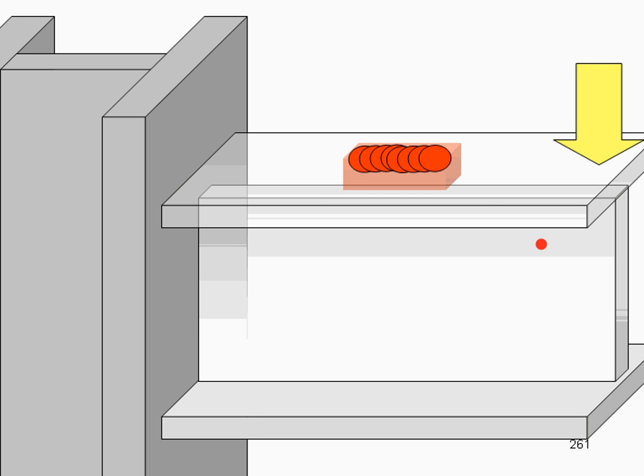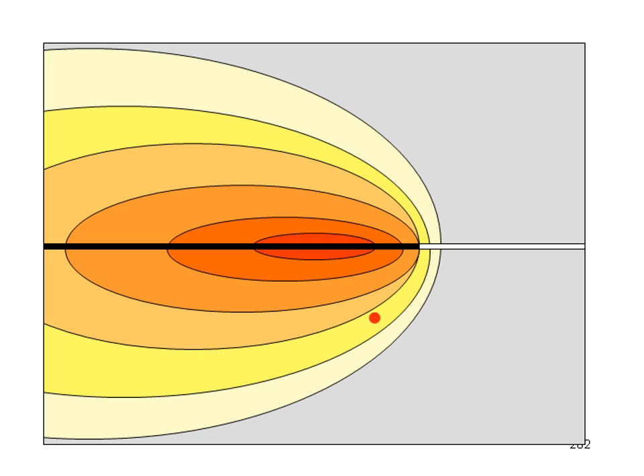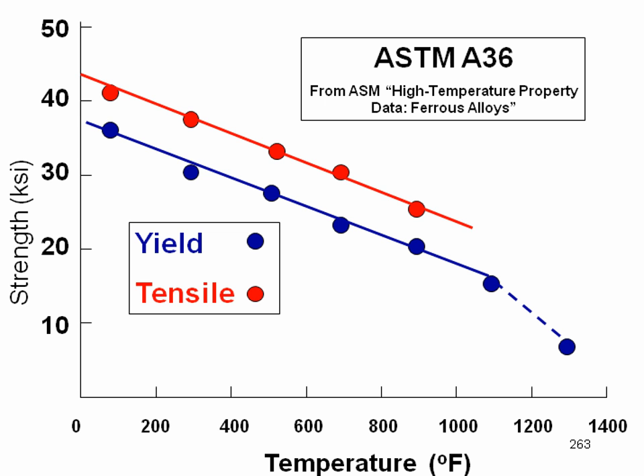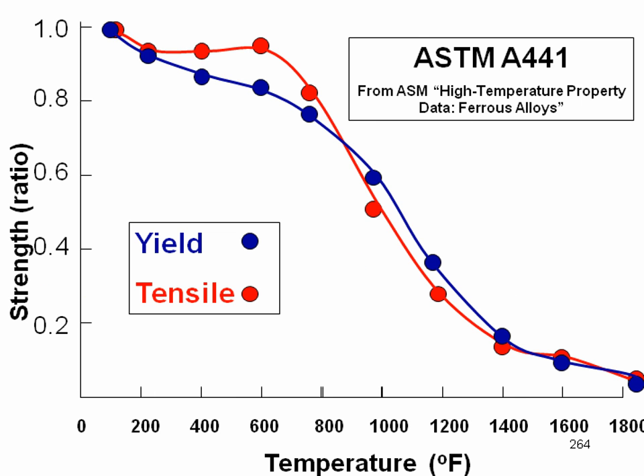And of course, you know that surrounding the arc, immediately next to the arc, we have a very hot zone, but it doesn't take too long before it drops down on either side. Now, this is a plot of the properties of A36 steel as a function of temperature. And in general terms, by the time we get up to 1100 degrees, we have about half the yield and half the tensile. Here's a similar plot for 441 that we don't make anymore, but gives that same general trend as well.